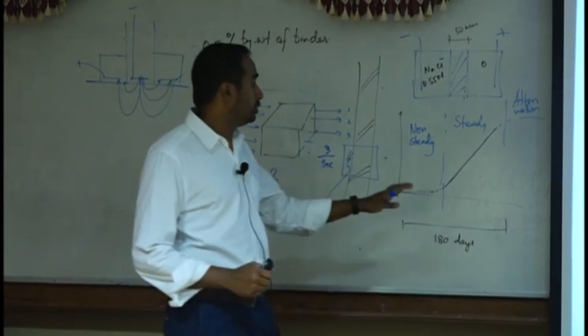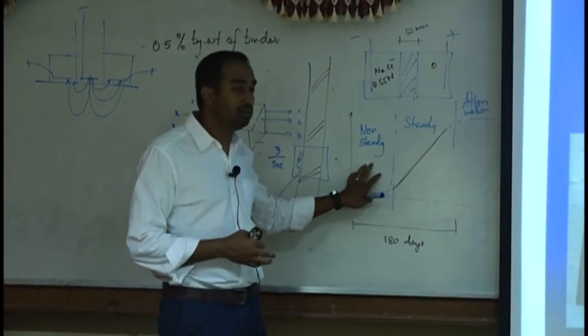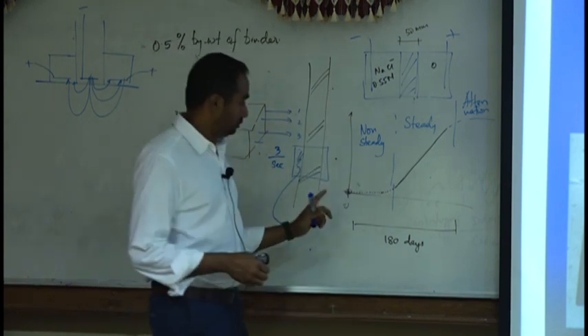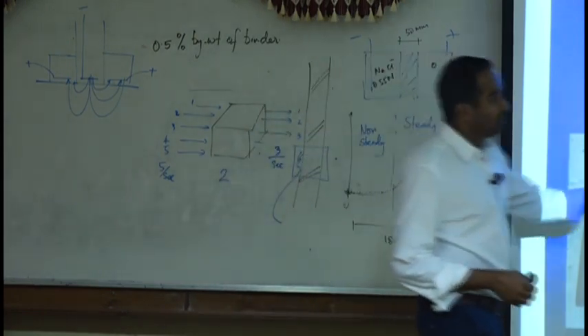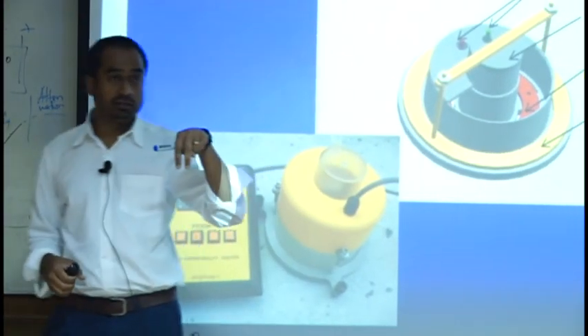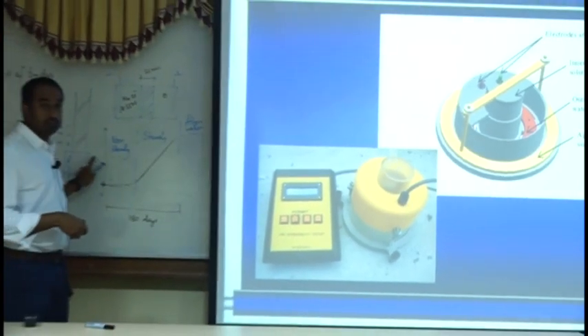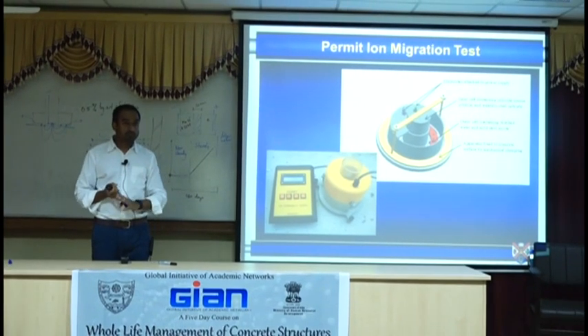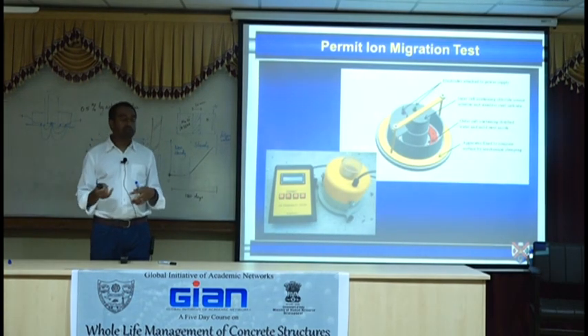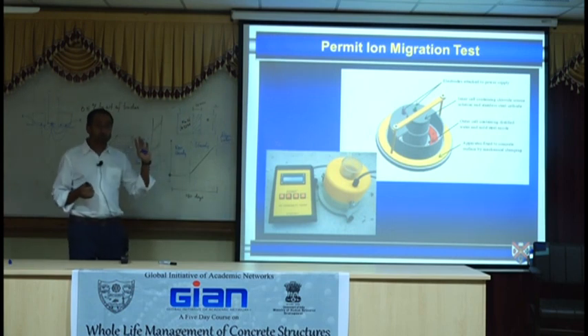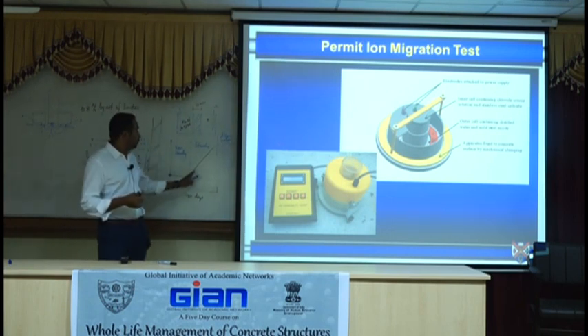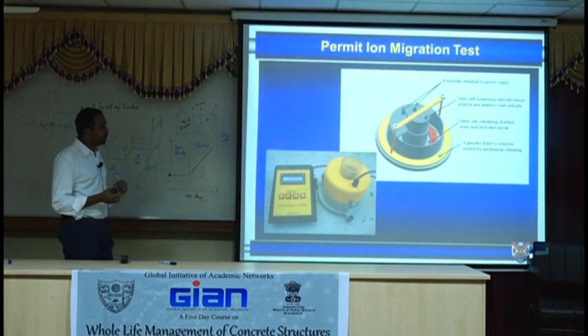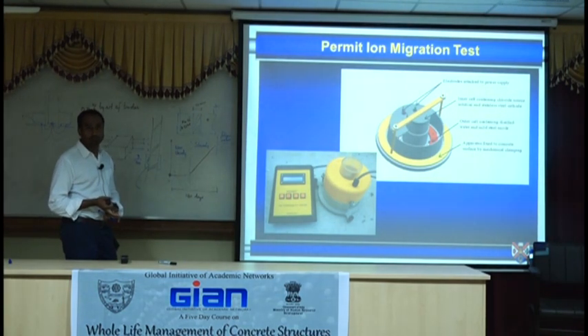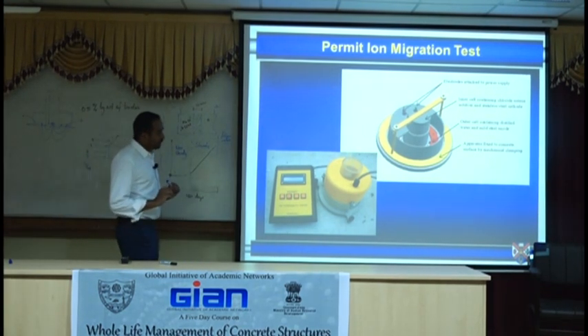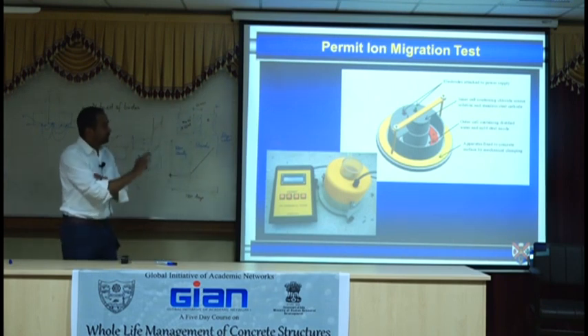So it's a steady state test. It cannot tell you anything about the non-steady part of it. That's what we're working on at the moment because it's a continuous monitoring system. It measures the chloride concentration coming in this cell. There's a conductivity sensor sitting in it. It keeps on measuring the conductivity and converts it into chlorides. Along with that, it measures the current. So the current can be used to get your 6 hours RCPT value if you want. I would not recommend it, but you can have it. And the current will also be monitored throughout. So we know roughly looking at the current when you're going to reach this state. Okay. The third thing is it measures the temperature in the cell. So altogether, it's quite an advanced piece of instrument for its nature.